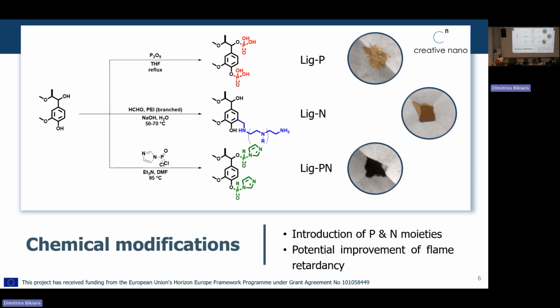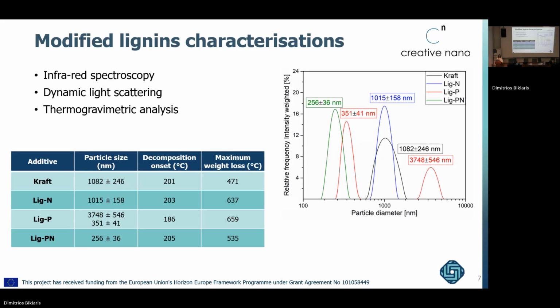And the other type of lignin we have used and that Creative Nano has produced are modified lignins. You can see here 3 types of lignin with phosphorus, nitrogen, and phosphorus and nitrogen groups. And these were produced in order to see if we could improve the flame retardancy of lignin. So these modified lignins, along with the chemical modification, we can see here that we have some size reduction. And also, if we look at the thermal stability of lignin, we have a large increase in the temperature where maximum weight loss is observed. So this would mean that perhaps degradation starts at the same temperature or a bit lower than for lignin, but probably we have some higher stability at higher temperatures.